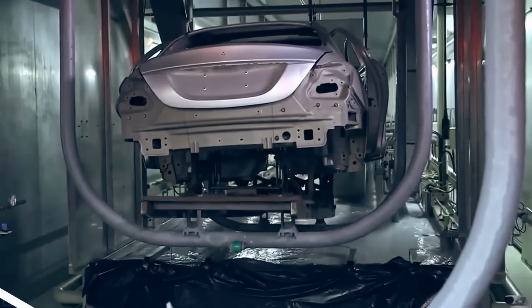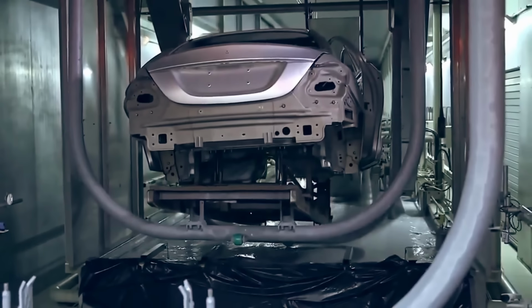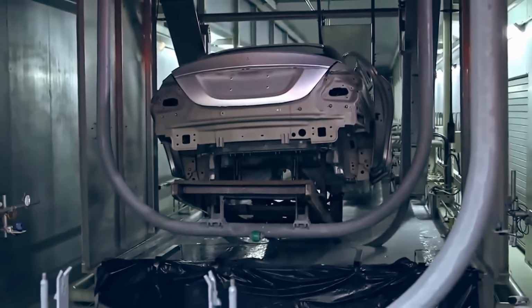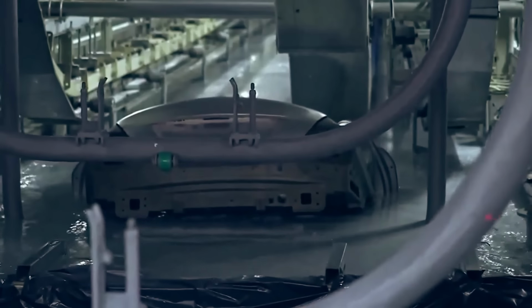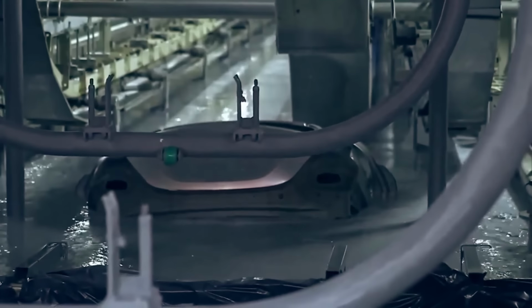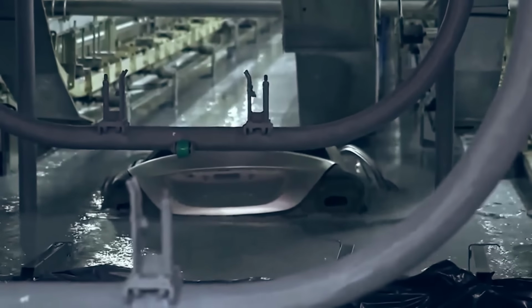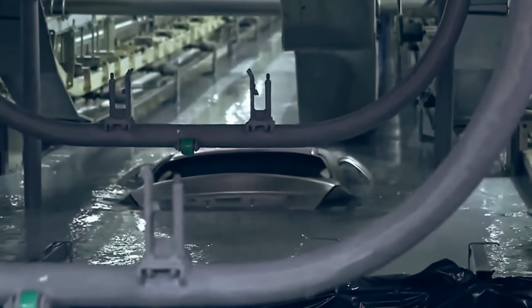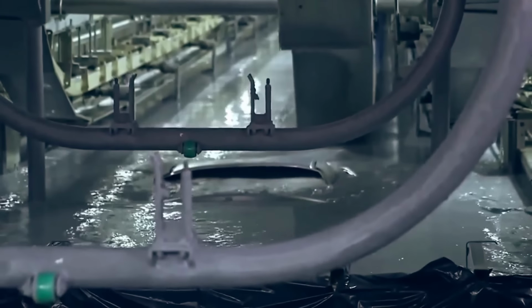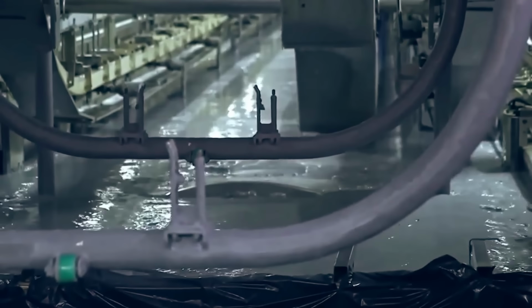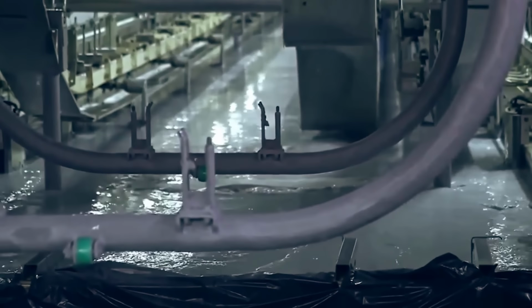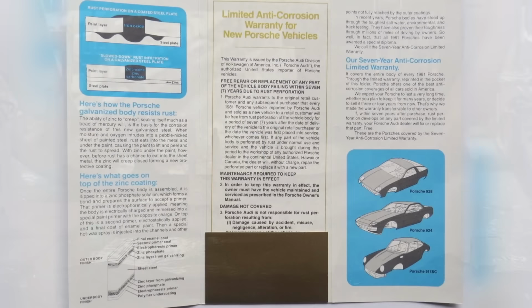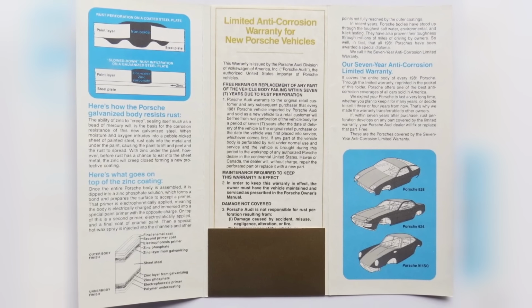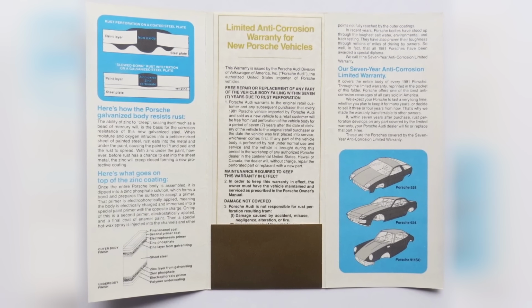The electrocoating process was not only fast and fully automated, but it also dramatically improved primer film coverage, especially in difficult regions such as recessed areas and sharp edges. It offered far more corrosion protection than previous techniques, and by the mid-1970s, it became the standard of the automotive industry worldwide, and it would ultimately lead to car manufacturers offering far longer warranties against corrosion than previous decades.